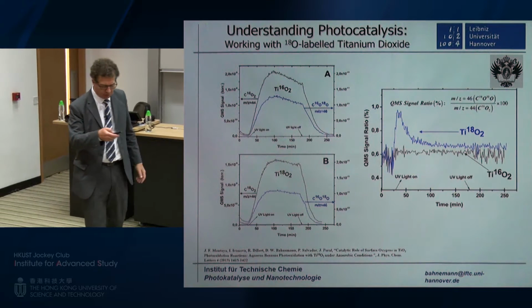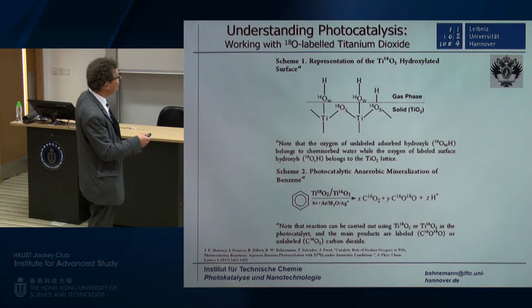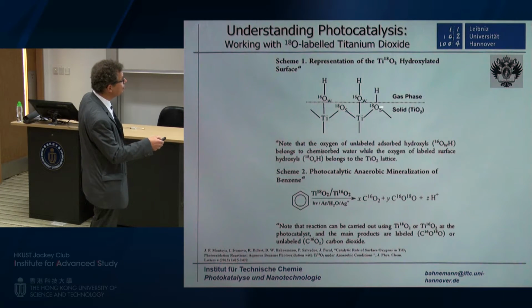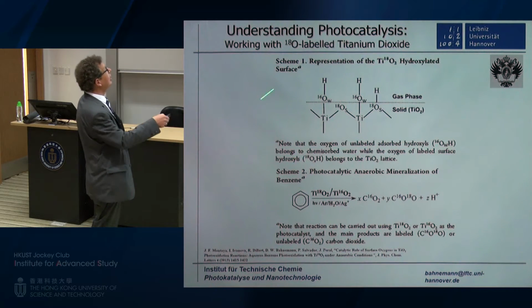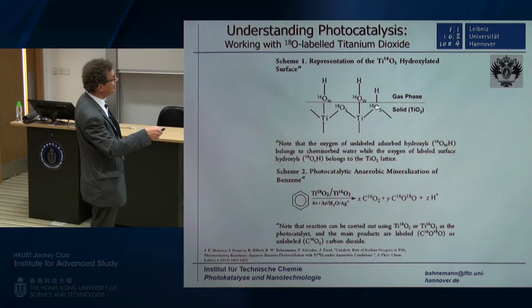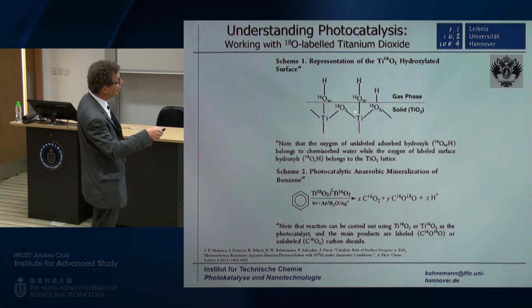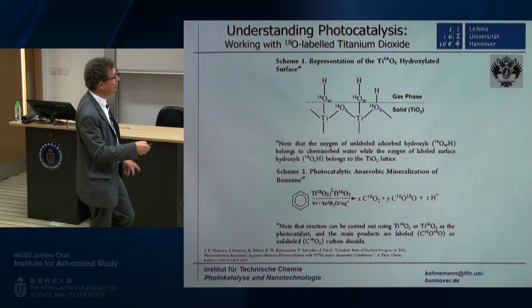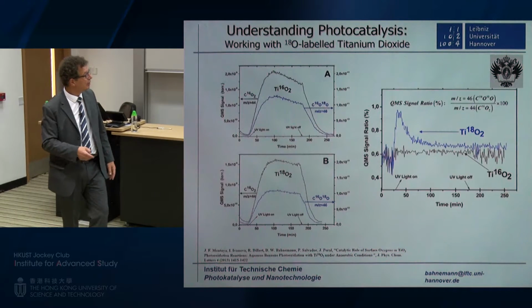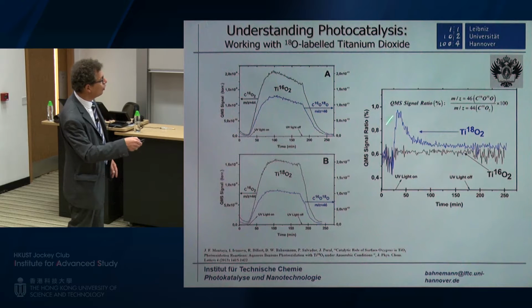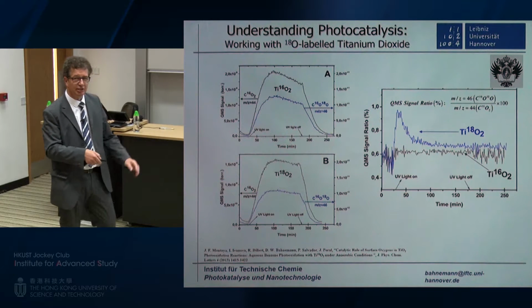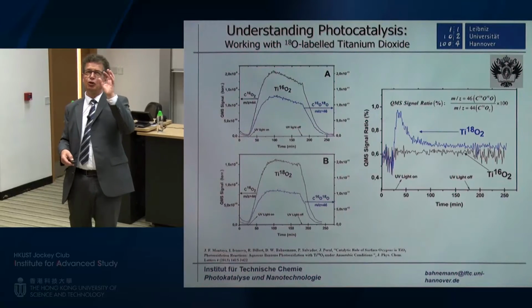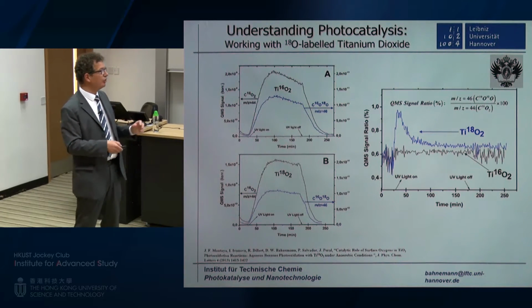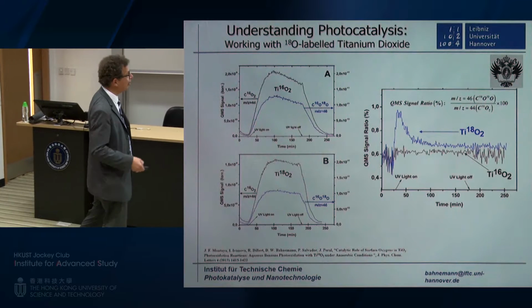So the whole system should be regarded as a dynamic system. You are breaking these bonds, yes, you are losing these oxygens, yes, but then they are replaced by oxygens from the water, and then you have a surface of this TiO2 particle containing now O16. The bulk still contains O18, but the bulk has nothing to do with the reaction. This is why we see this transient over the first, let's say, few minutes of the reaction. But we should forget this notion of a constant TiO2 surface. The surface is apparently dynamic.